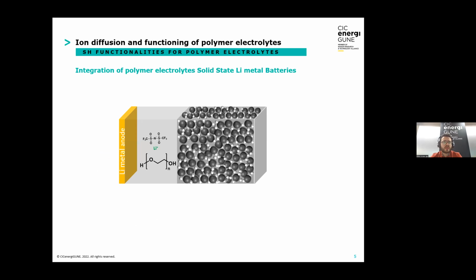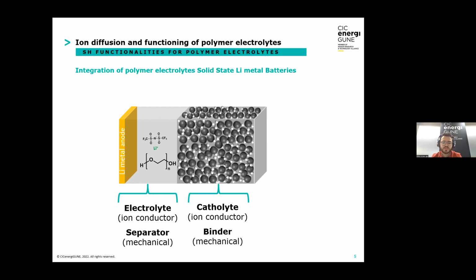So in the solid-state battery, which functions does this polymer electrolyte fulfill, or where do we have the polymers located? First we have the polymer acting as electrolyte and separator, which fulfills two functions at the same time compared to a lithium-ion battery. It fulfills the function of being an ionic conductor, meaning the electrolyte, and fulfills the mechanical separation of both electrodes, being the separator. And in the positive electrode, the cathode, the polymer electrolyte also fulfills two functions. It is the ionic conductor in the cathode, so we call it the catholyte, and it is also the binder of the active material particles, which is also a mechanical function.